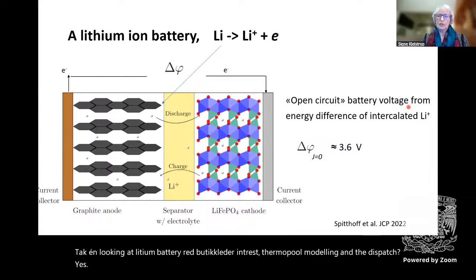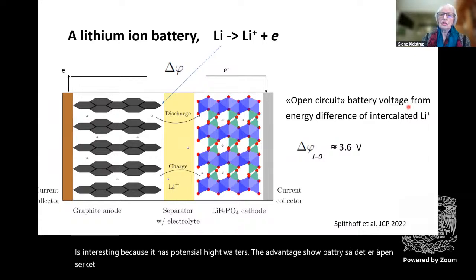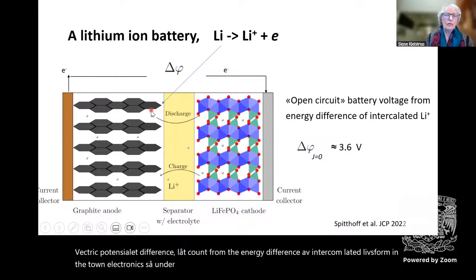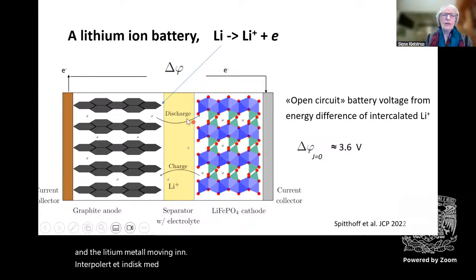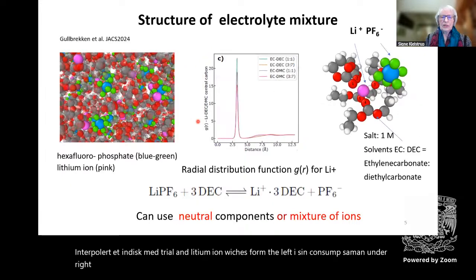And this battery is interesting because it has the potential for high voltage. That's the advantage of the battery. So the open circuit battery voltage is as high as 3.6 volts. And that electric potential difference comes from the energy difference of intercalated lithium in the two electrodes. On the left-hand side, the anode, we have graphite and lithium metal moving up to the surface where the electrode reaction takes place. And on the right-hand side, we have lithium iron phosphate and lithium ion moving intercalated in this material. And lithium ion, which is formed on the left, is then consumed in the same amount on the right, and that completes the circuit.